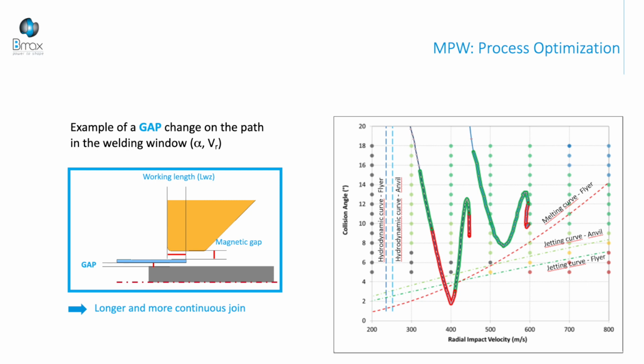In this case, we change just the gap between the flyer and the parent part, and this way, as you can see, the new path is fully in the welding window. So this second configuration is better than the first one. We have a longer and more homogeneous weld in this case.